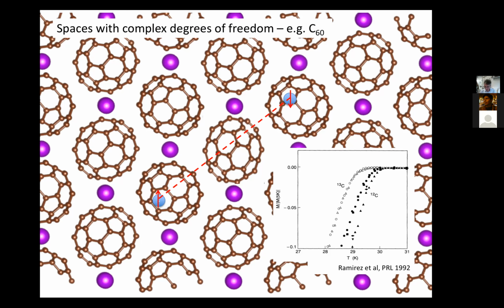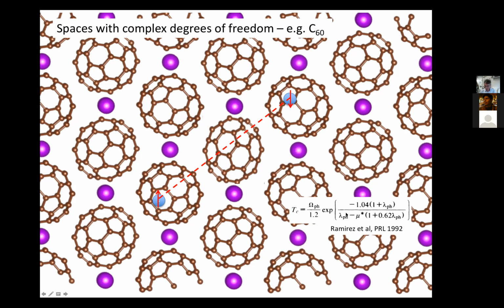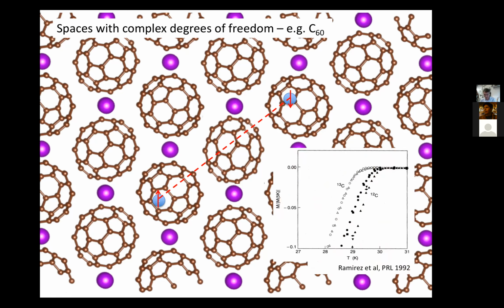And what makes that work, if you go back to this equation, you can see the characteristic phonon energy comes in as a prefactor of the exponential. So people have been looking for hydrogen-based superconductors for a long time, because hydrogen should have an extremely high phonon frequency: it's really light, and you can get a strong hydrogen bond, and so you can get a very high characteristic phonon or lattice vibration frequency. That's why people are looking at that. Anyway, these are just some of the things I've been involved in.